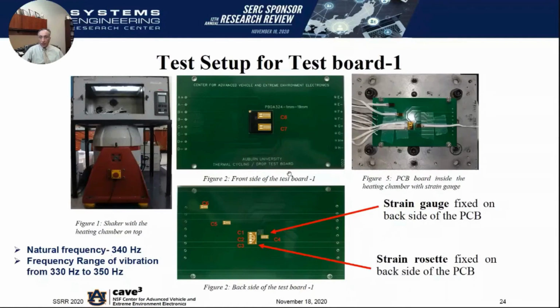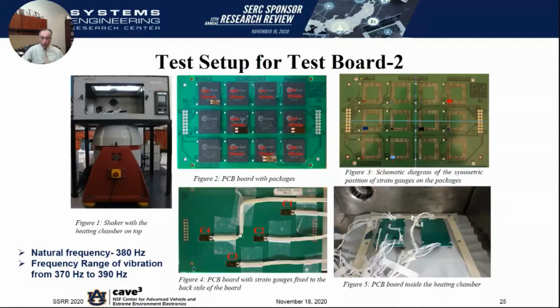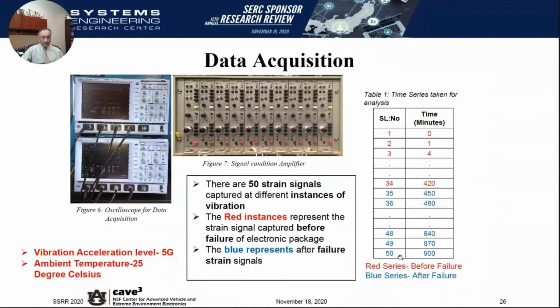So this is the single component board. This is the multi-component board. Similar protocol in terms of sensors, some on the part, some on the board. Similar range of sine sweep, different natural frequency owing to the different mass and different stiffness of the board. But there are 12 parts instead of just a single part. And you can actually see these are daisy chain, and you can see the daisy chain wires as well. So we connect that to a data acquisition system, and we are acquiring strain data and continuity data simultaneously at a very high sampling rate.